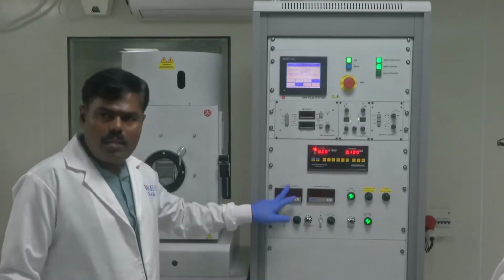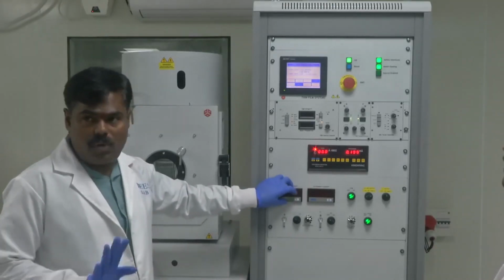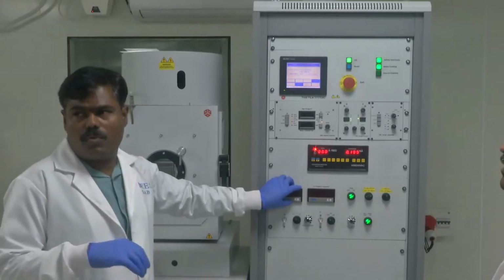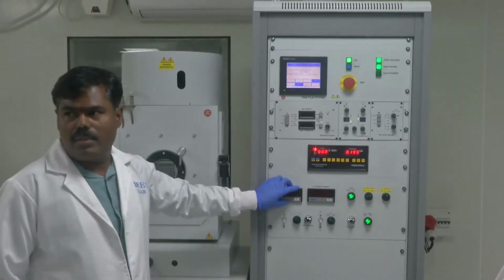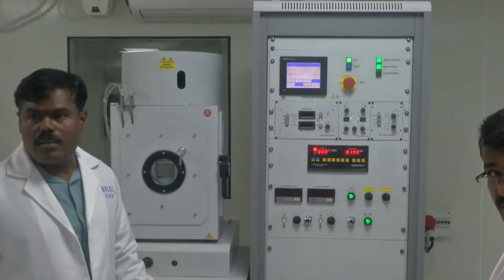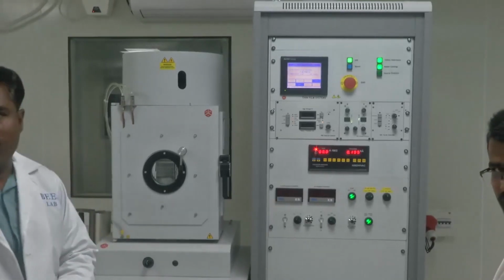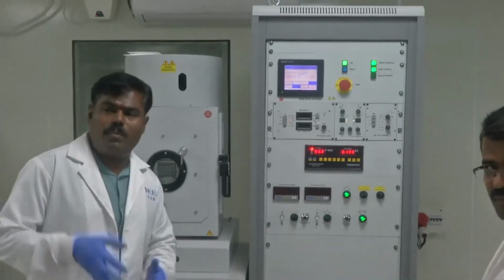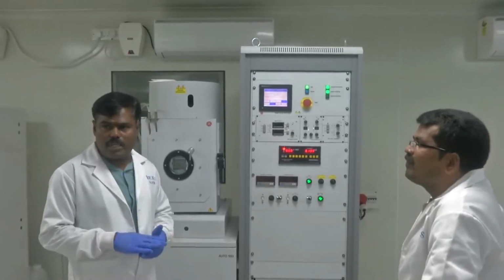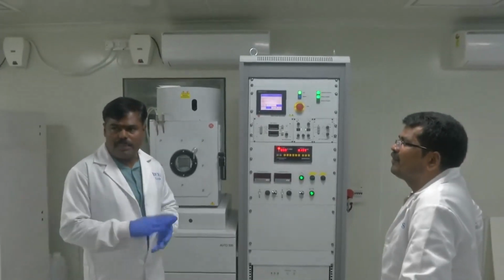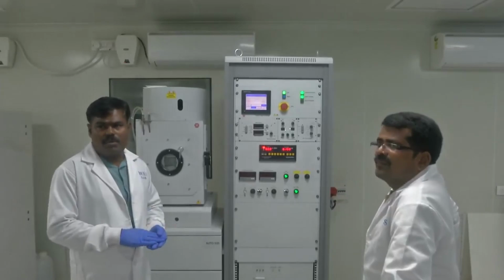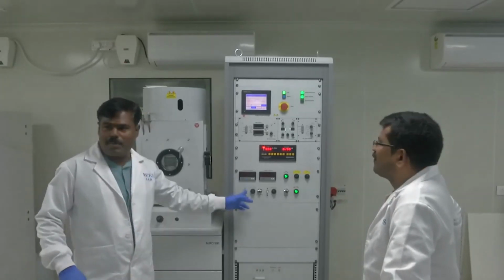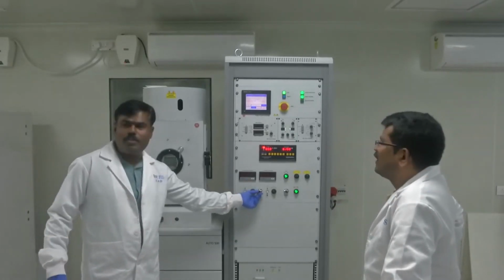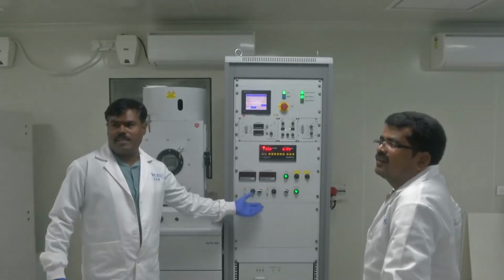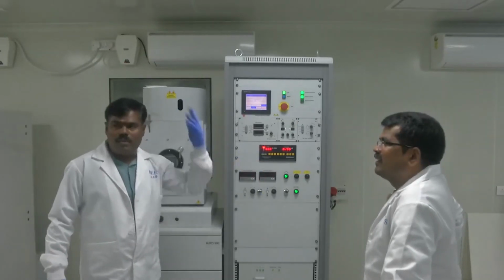And for thermal, the maximum current: the power supply is 400 amps, but you should not go to 400. Generally we keep 20 to 30 for aluminum. Initially it will take more current for melting. Once it melts, you have to decrease the current, otherwise your rate of deposition will be faster.